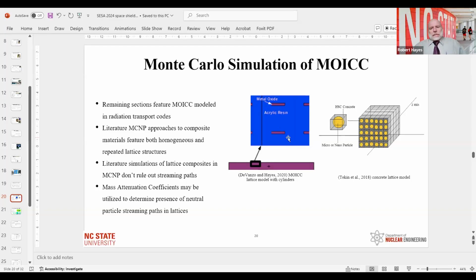Now, that begs the question, if these particulate have special radiation attenuation properties, is there going to be a difference in the Monte Carlo modeled values compared to measured? Because in measured values, these particulate are going to be random. So does that change the radiation attenuation properties of the material if the particulate are in a crystal lattice, or if they're just randomly distributed like an amorphous material, as one would expect? This research showed that there was indeed an effect, and that an amorphous distribution is going to give you different radiation attenuation properties than the crystal lattice.